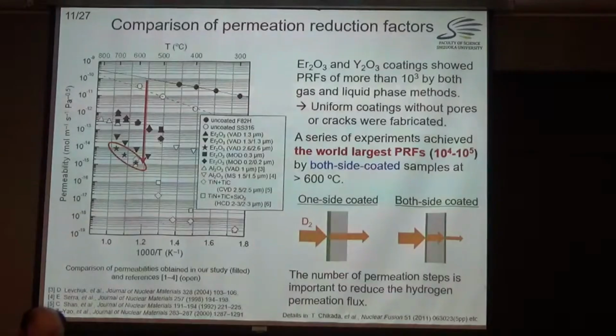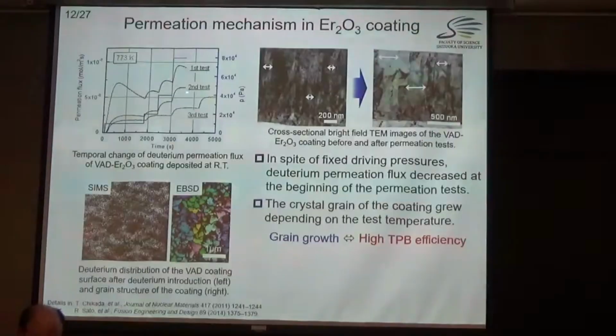So an interesting thing is the permeation mechanism through the erbium oxide coating. This figure shows the temporal change of the permeation flux in the first test, second test, and third test at the same temperature, 500 degrees. At the first test, when deuterium was introduced, the permeation flux decreased drastically during the measurement. Then when we repeat the measurement, it goes down with the same deuterium pressure, then finally we get the steady state permeation flux like this. So that means something changed in the films.